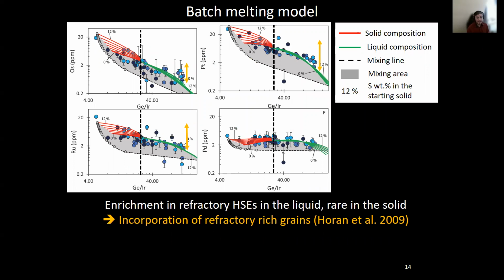Now these correlations are working for plenty of different elements, but something is not working: it's impossible to fit our data that are above the liquid curve here, highlighted by the yellow arrow. And these points that don't follow the model are only for refractory elements and for the liquid. So we suggest that these high values reflect the incorporation of highly siderophile-rich refractory particles within the liquid during metal melting.